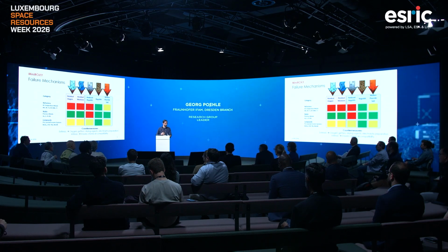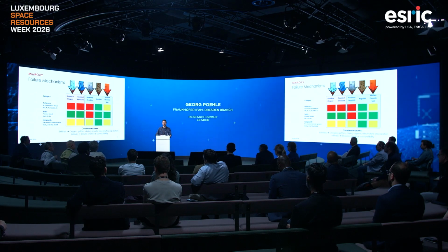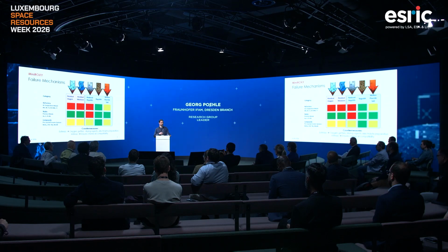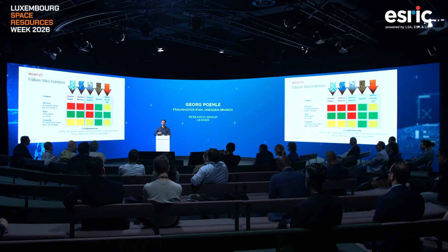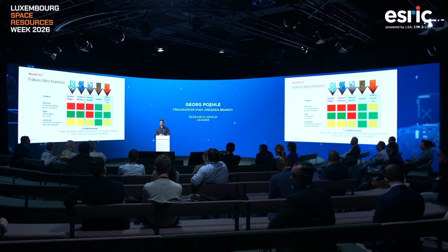Second one would be noble metals would be very nice, and we could show that they are highly resistant to the molten fluoride salts, and things like oxygen and moisture are of course no problem there. However, once again, the formation of alloys or intermetallic phases mean that these kinds of cathodes wouldn't be stable and would have to be regenerated all the time, which doesn't make for a very good system. And finally, we have what I broadly call compounds here. We have particularly looked at zirconium nitride, molybdenum silicide, and a composite called MOSIP to see if they can fulfill the conditions.